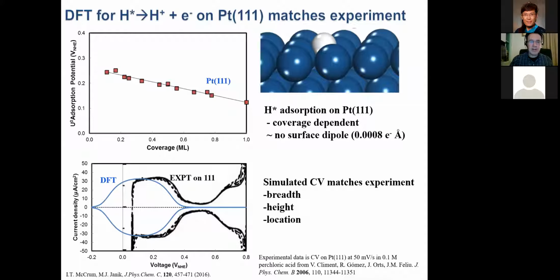It doesn't really interact with water. It's a very small molecule, sits down there and binds very strongly to the metal. So I can calculate then the strength of hydrogen adsorption as a function of how much hydrogen's on the surface, the coverage. On platinum 111, there is some coverage dependence, everywhere from low coverage up to a full monolayer of hydrogen. And the high coverage hydrogen will come off more easily. So if I started this experiment, the high coverage hydrogen is adsorbing here because it's less stable, if we want to think of it that way.